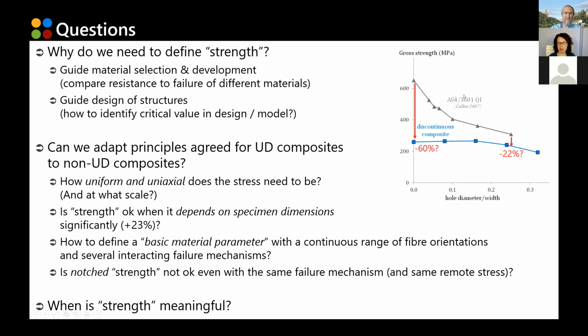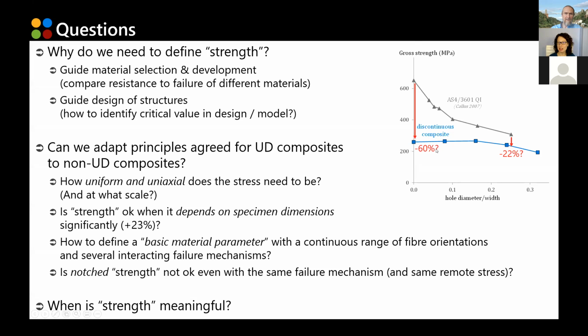For instance, I have now added the gross strength measured for different hole diameters, not only for a discontinuous composite, but also for a quasi-isotropic continuous fiber composite. And if I want to compare these two materials, for instance, should I say that my discontinuous composite is 60% weaker than the continuous fiber composite? Or is it about 20% weaker than the continuous fiber composite?